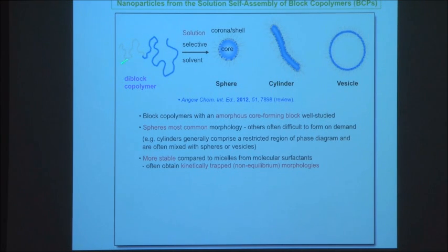You can play with the ratio of the two blocks, but often you just have to look at a wide range of materials and see what you get during the self-assembly process. It's very difficult to predict what you're going to get. And cylinders, for example, are a very interesting morphology. But when you can make them, you find that often they're actually mixed with other morphologies. So you'll make cylinders, but there'll also be some spheres or vesicles mixed in with them. So cylinders, for example, usually comprise a very restricted range of the region of the phase diagram.